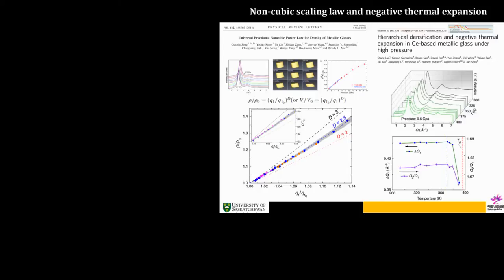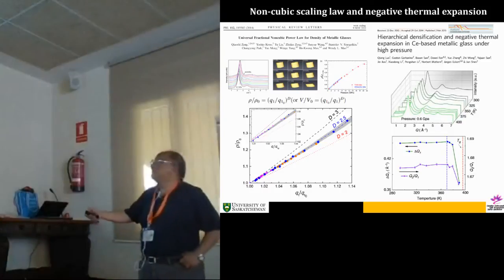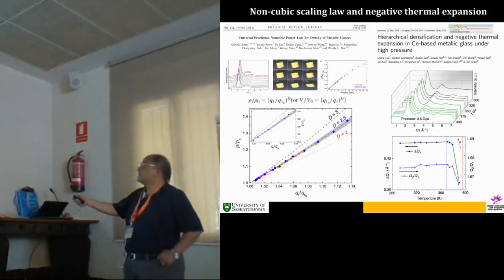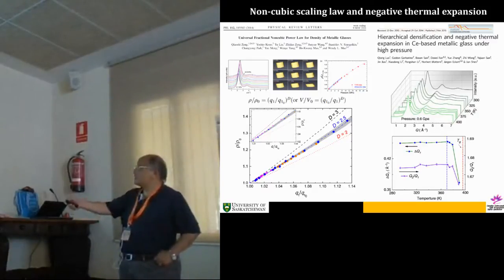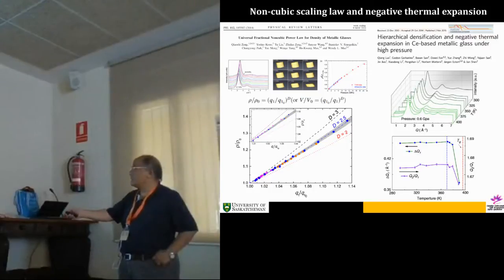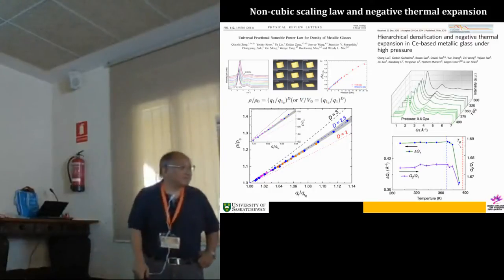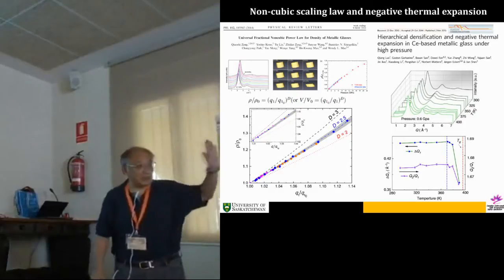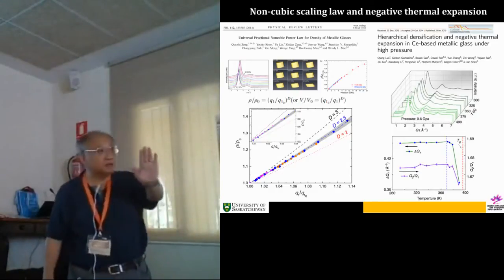This is the first paper I see people put actually a glass into a diamond anvil cell. So if you believe them, they say that's a phase transition here. All right? Well, it's true, anyway. And then there's several subsequent work in later year. If you take this material, the cerium aluminum, and you compress it again, you form crystal again. So you have a crystal amorphous transition and become crystal again.